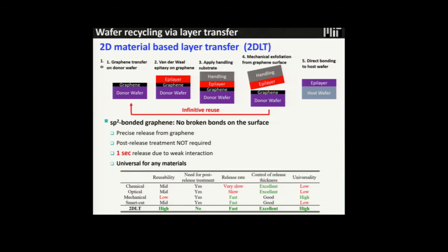It's gonna come. Yeah. All right. So graphene forms a very weak bonding, so you can just peel off. Then your remaining wafer is just non-damaged. It's pristine. Then you can just keep growing, peel off, keep growing, peel off. And more importantly, this peeling off process just takes 1 second because of mechanical release. That's also a very important feature.